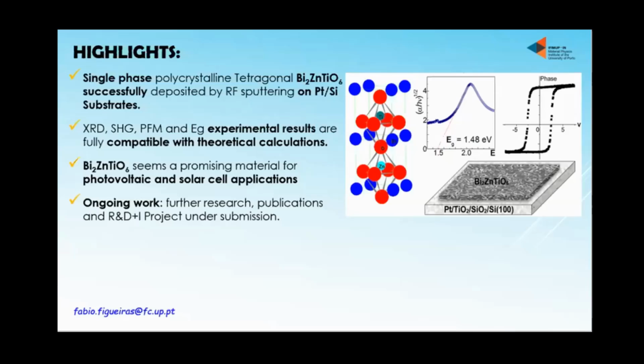So this is the absorber. This is the material that is absorbing, and it has the properties for the photon generation of electrons and holes. And the holes will go by the titanium percolation, and the electrons will go by the zinc percolation. So these materials can split, and then the material has ferroelectric properties. It can have a polarization. If we fix the polarization between the electrodes, the electrons and the holes will be split inside the material itself. It does not need a p-n junction. It's a single material, and all it should need is the electrodes on top and bottom, and it makes the absorption, it makes the driving, and it makes the splitting. It's all in one. So it has the properties to do this.